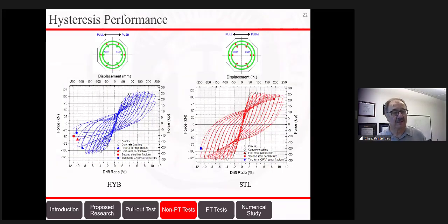So here you can see on the left the hysteresis performance of the hybrid. Everywhere you see the acronym HYB means that this is the column with 6 steel bars shown here in red and 6 fiberglass bars shown here in green. And of course you can see how we applied the load and pull and push. We started with a push, and you can see that on the left is the performance of the hybrid column in blue, and on the right is the performance of the steel column, which has 12 steel longitudinal bars in red, and we have the acronym STL.